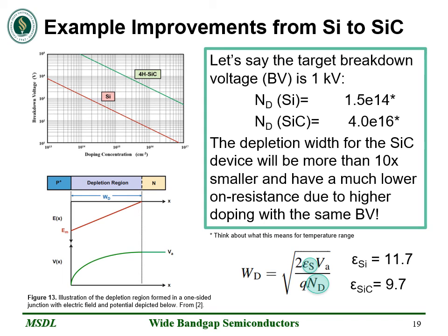So for silicon, to achieve 1 kV, we're going to need about 1.5 E14 for the doping concentration on the lighter side of the junction. And for silicon carbide, this raises to about 4 E16 to achieve the same breakdown voltage. And when we plug these values in to the formula for depletion width, we can see that this results in about a 10 times smaller device, and that the device will have a much lower on resistance due to the higher doping concentration. And this is all while achieving the same breakdown voltage. But as we just saw, what about how this affects the temperature range that these devices can function over? With the much higher doping concentration for silicon carbide, we can see that we can use this over a wider range of temperatures as well.